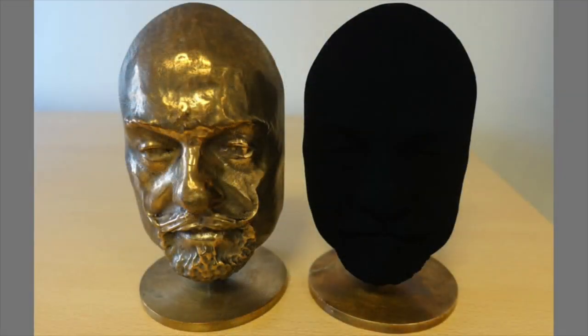Jensen's original Vantablack coating was made by a process known as chemical vapor deposition, CVD, which took place in a reactor vessel at 400 degrees Celsius and in a near vacuum. Millions upon millions of carbon nanotubes, each about 10 nanometers in diameter and 30 micrometers long, were formed as a surface layer. The coating absorbed up to 99.965% of visible light falling on it, whatever the viewing angle. The result is astonishing. An object coated in Vantablack shows no relief, no features whatsoever.